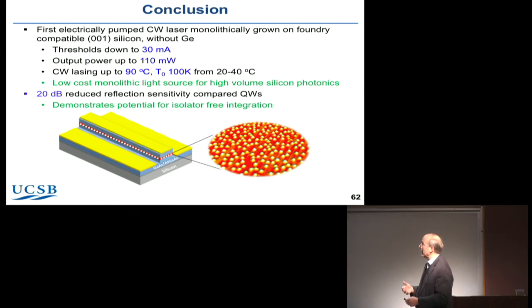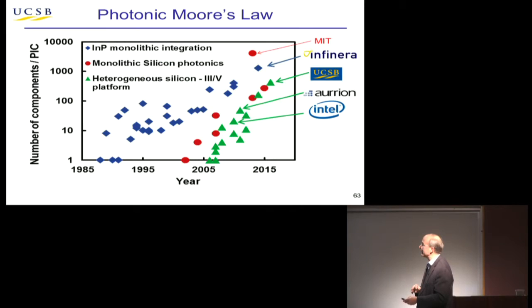So just to summarize what you can see with quantum dot growth on silicon, reasonable thresholds, not as low as we'd like to see, reasonable powers, fairly good temperature dependence, T0s of 100 degrees. And again, I didn't talk about these quantum dots. They're all grown by strained indium arsenide on gallium arsenide or on indium phosphide. And people are doing both for work at 1.3 or 1.5. This is where the field is now.